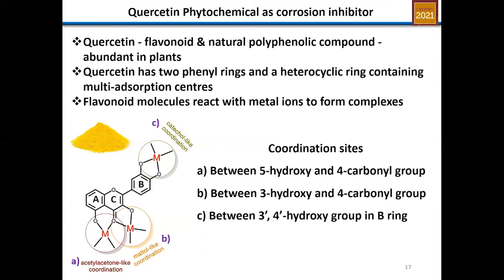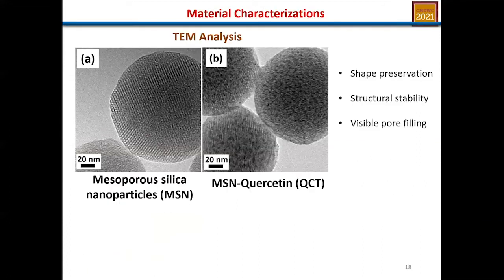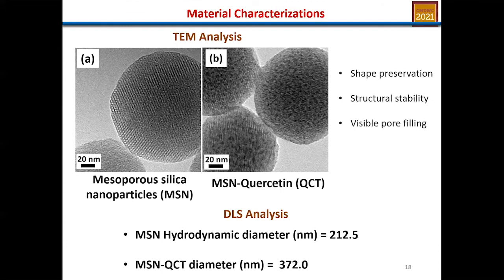Okay. In this study, we utilized quercetin as a corrosion inhibitor. Quercetin is a known flavonoid with a lot of hydroxyl groups, and the coordination sites could be either the carbonyl group or the hydroxyl group in the B ring. So we prepared silica nanoparticles and loaded the quercetin in them using the liquid crystal templating mechanism, and we found shape preservation, structural stability, and visible pore filling. This is the image of the unloaded and the loaded quercetin complex.